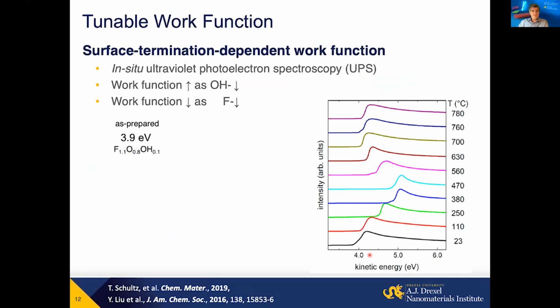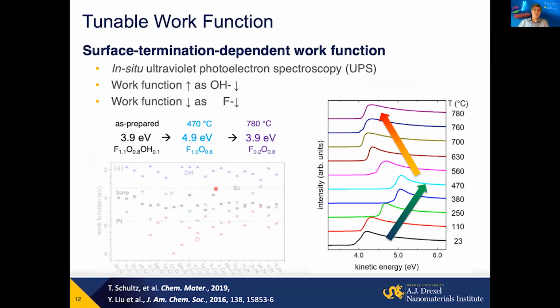For example, when we heat a sample of titanium carbonitride MXene to high temperature initially, the work function increases from about 4 to over 5 electron volts here, because we remove OH groups. And then we heat further, we start losing fluorine, and actually it goes back.